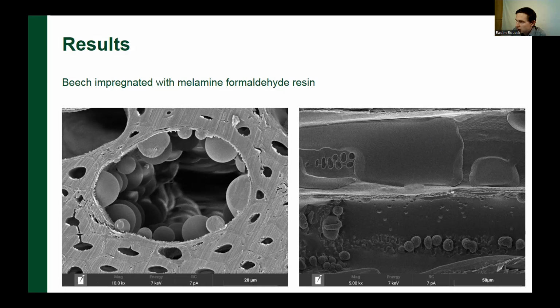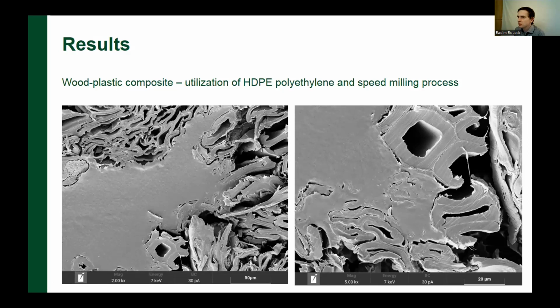Let's go to another example. And this is wood plastic composite. It's an HD polyethylene, which was mixed with milled wood. It was an experiment to utilize a speed milling process. And then the material was compressed in a heated press to melt the polyethylene, which then connects the particles. We can see that the particles make some clusters on the left image, and the polyethylene doesn't penetrate well to the structure of particle clusters. It could be because of high viscosity of melted polyethylene.